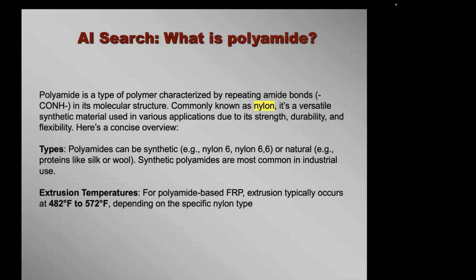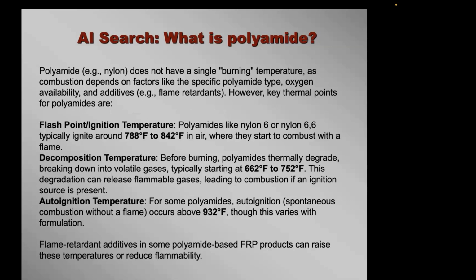So again, I did an AI search for polyamide. It is nylon. So extrusion temperatures are 482 to 572 degrees, which, they have to melt it to make that piece. Like I said, your typical building fire is like well over 1,000 degrees. So that's going to melt, which is going to result in panels falling off the building. So their burn temperature is 788 degrees to 842 degrees, but it starts to decompose between 662 to 752 degrees, and then it'll auto ignite at 932 degrees. So you can put some additives in to raise these temperatures or reduce flammability, but they still burn.